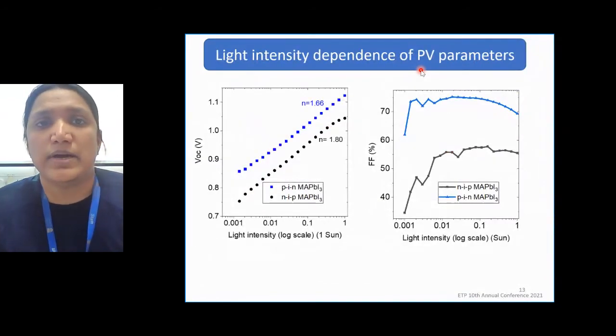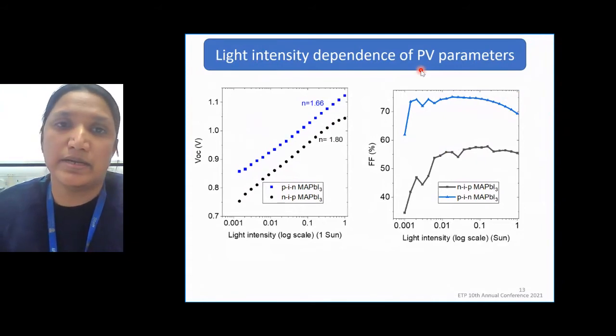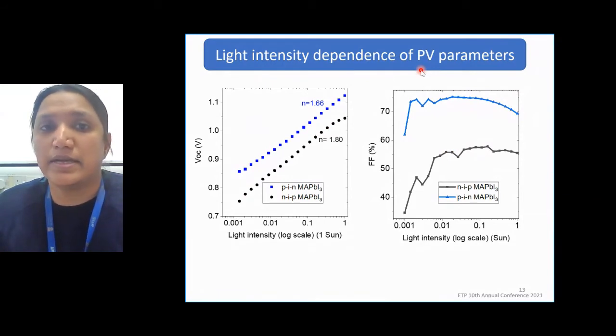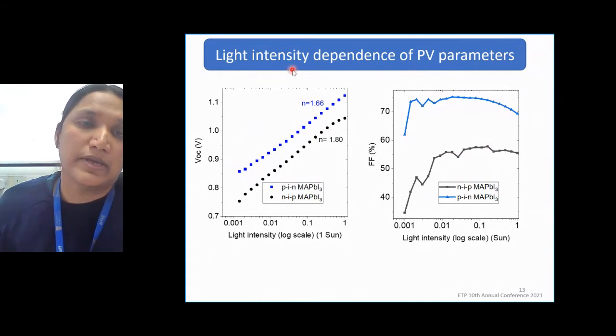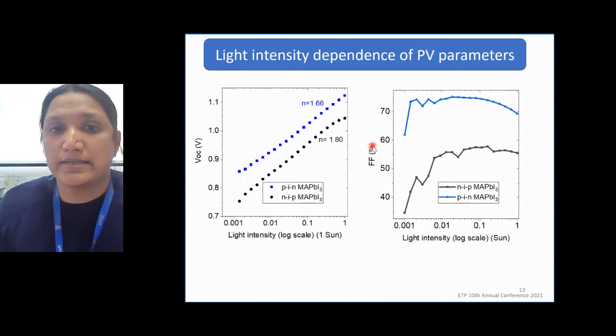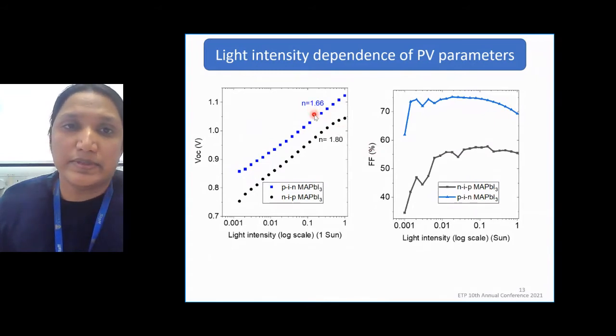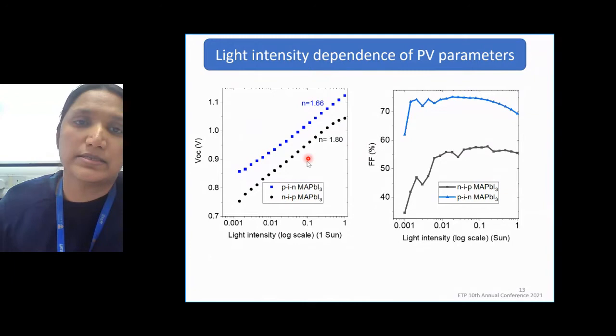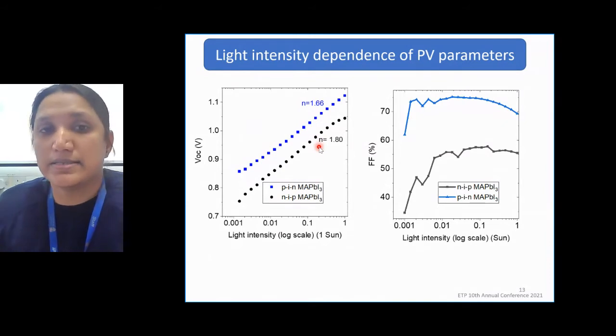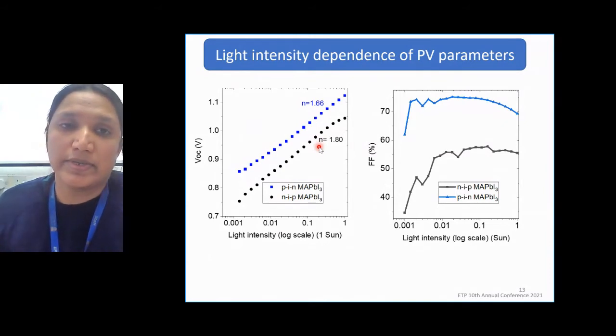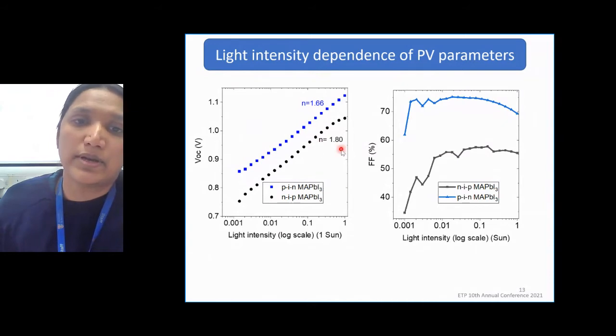So in order to understand the reasons why these NIP devices are showing lower efficiency values compared to the PIN devices, we have done some light intensity dependent characterization of the open circuit voltage and fill factor. This VOC versus light intensity plot is shown for PIN and NIP devices. We can see these characterizations revealed that these PIN devices show less non-radiative recombination losses compared to the NIP, while NIP devices suffer higher trap-assisted recombination losses.